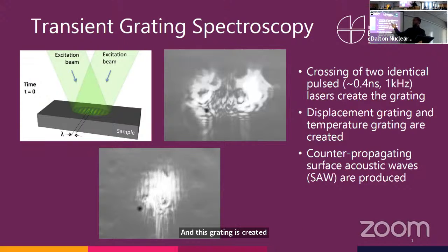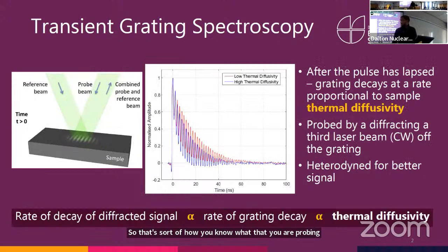Once the pulse has lapsed, heat from your hot regions would then flow into the cold regions, and the time it takes for the heat to flow from the hot bit to the cold bit tells you it could also go the same distance into your sample. So that's how you know what depth you are probing in your sample. And the elastic response of the sample surface to that periodic excitation kicks off counter-propagating surface acoustic waves, which superimpose an oscillation in your signal.